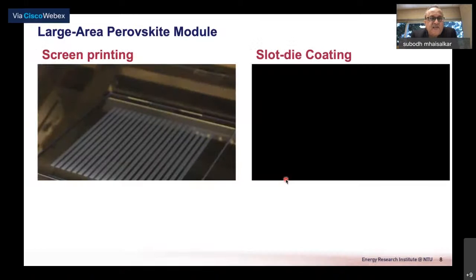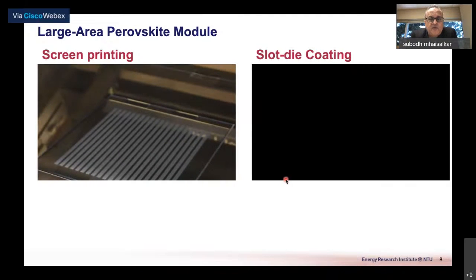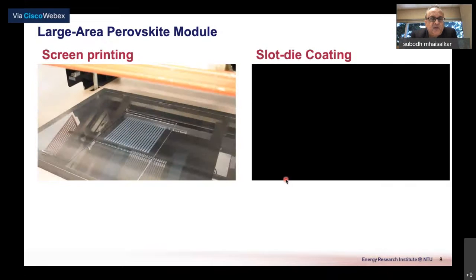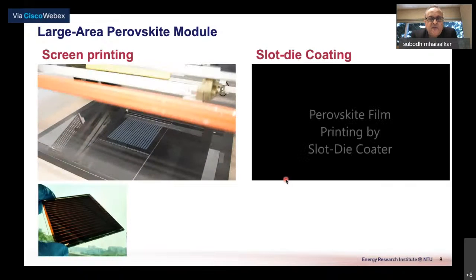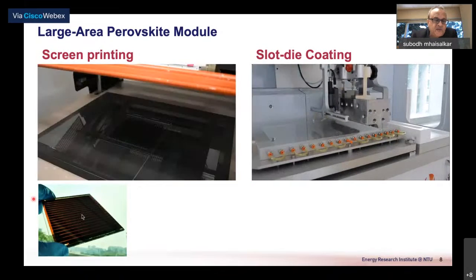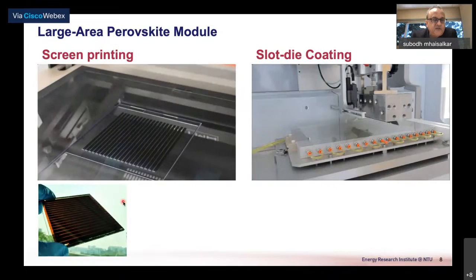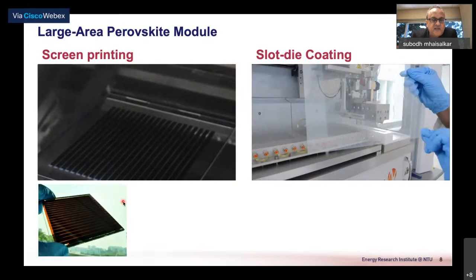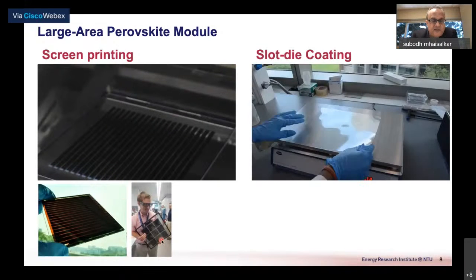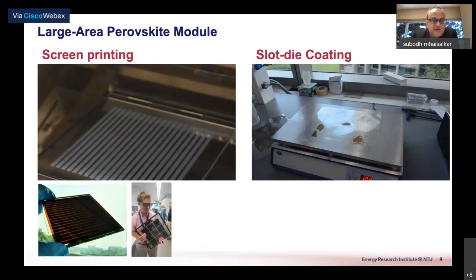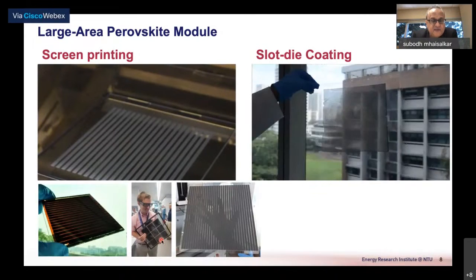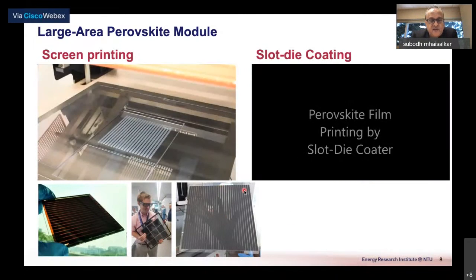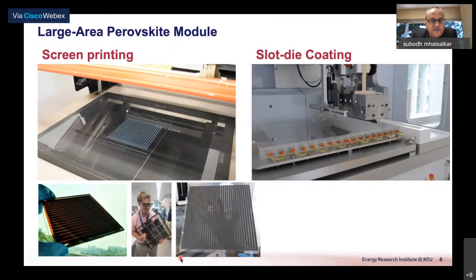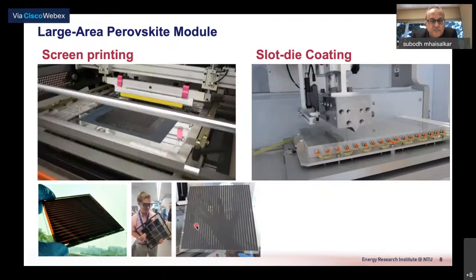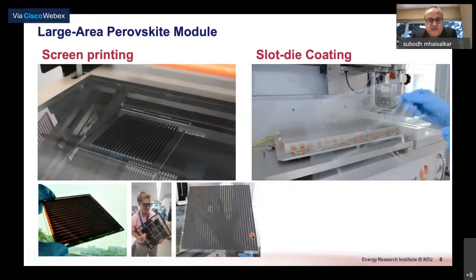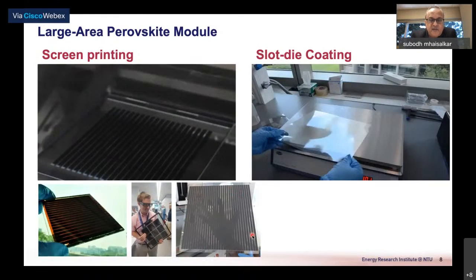When it comes to large area processing, this is some of the work that we have done in the lab. We have put down screen printing processes. We do a fair amount of slot die coating. The image on the left-hand side is samples which are 5 to 10 centimeter squares in size. Then you can assemble them into panels, and you can see a 3x3 matrix here of 10 by 10 centimeter devices. The largest we have done so far is a 30 centimeter by 30 centimeter device, and you can see an entire hand behind these stripes of perovskites that have been deposited.